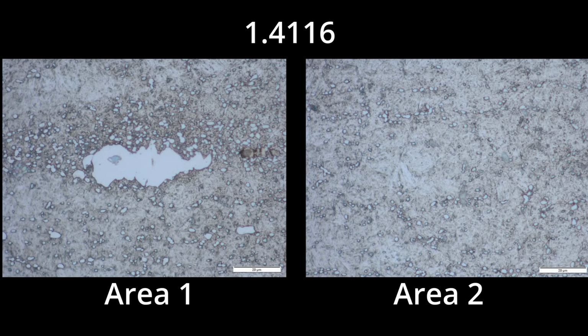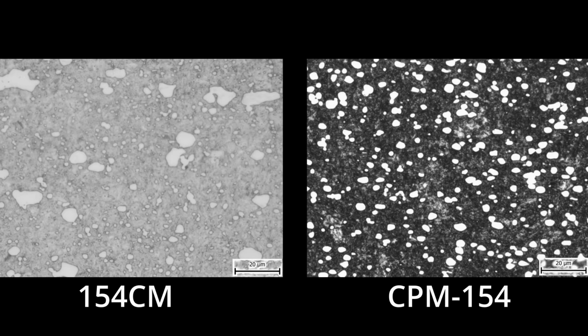And so if you want to show people that you're doing this amazing thermal processing that can get rid of ugly carbides that were generated in the steelmaking process, just take a picture where there's no big carbide and tell people that you did an amazing thermal cycling that improved the steel. But for the rest of us, it's better to either use a steel from a great steel company with a good composition that avoids large carbides by and large, or to use powder metallurgy steel. Powder metallurgy is a technology used to keep the carbide size small. So if we had used CPM 154 with AEBL in Damascus, then the carbides would be smaller than with our very extensive forging process.